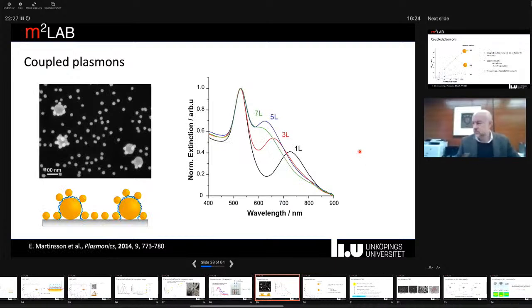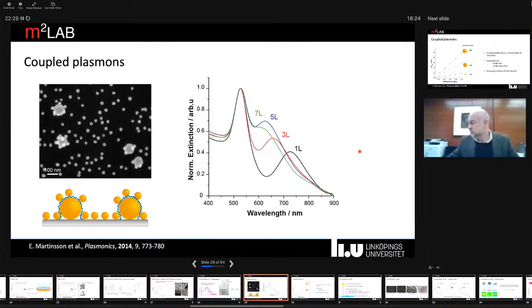But we can still employ plasmonic coupling to redshift the plasmon band if we do this in a more defined way than just unspecific aggregation. And we can do it by essentially making satellite structures of smaller and larger particles separated by a well-defined distance using polymer layers, as in this case.